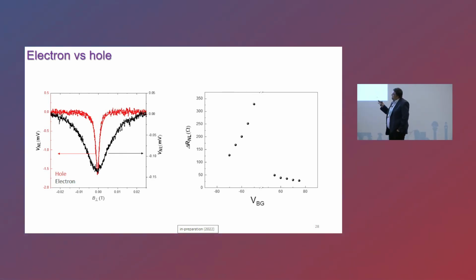It's similar in black phosphorus. Indeed, the effective mass for electrons is smaller than for holes. But this is a two-dimensional material, so you can apply gate voltage. You can change the carrier concentration as well as the type of the charge carriers. For example, in this region the dominant charge carriers are holes, and in this region electrons. So we can perform the spin transport experiments by just applying the gate voltage.